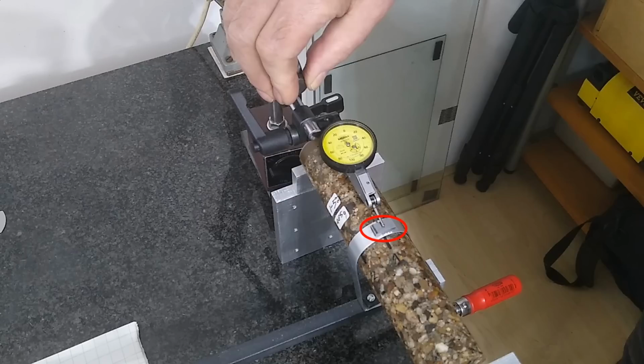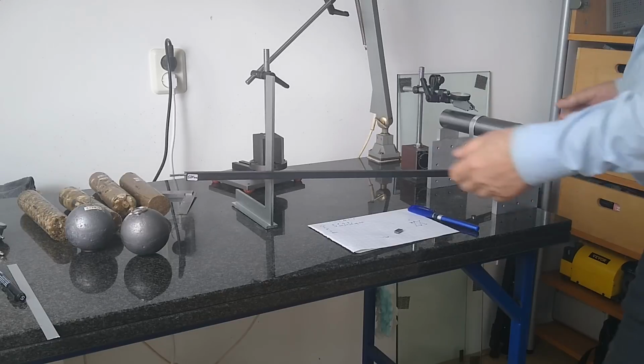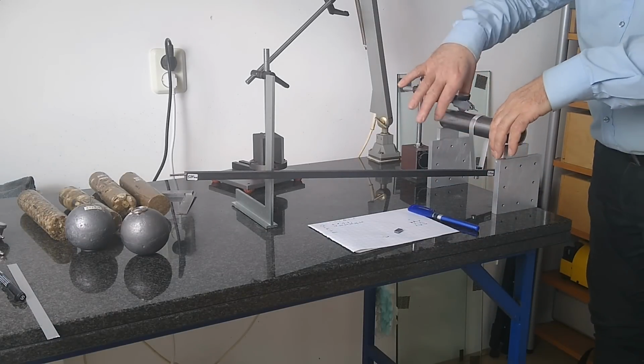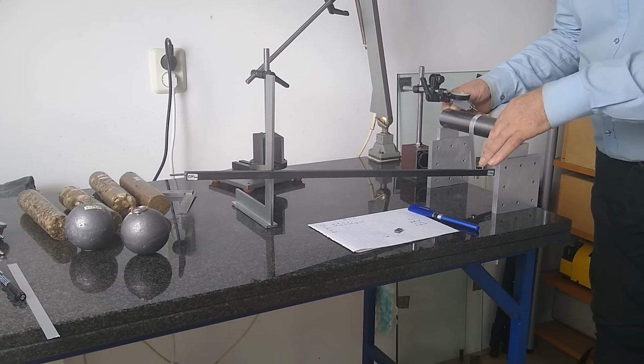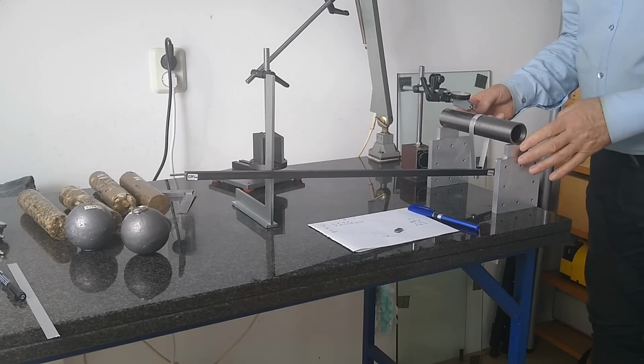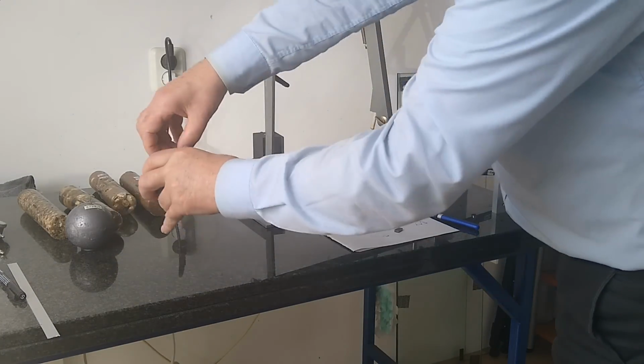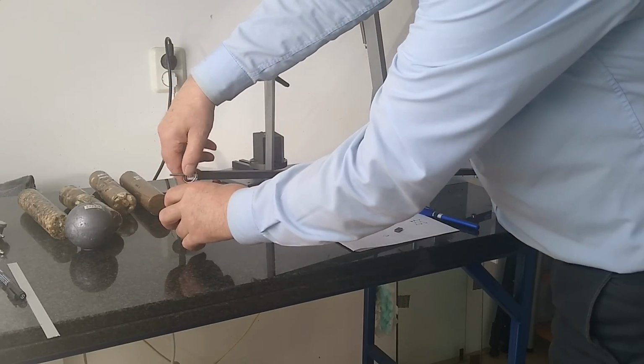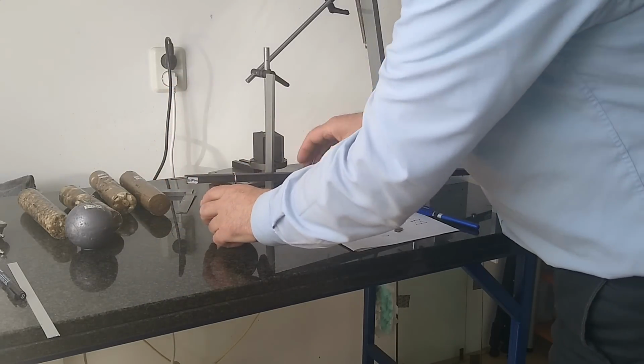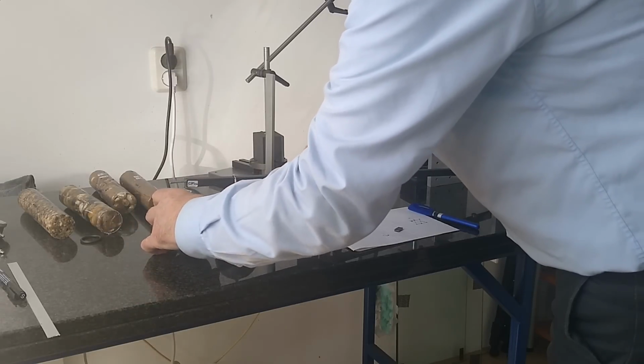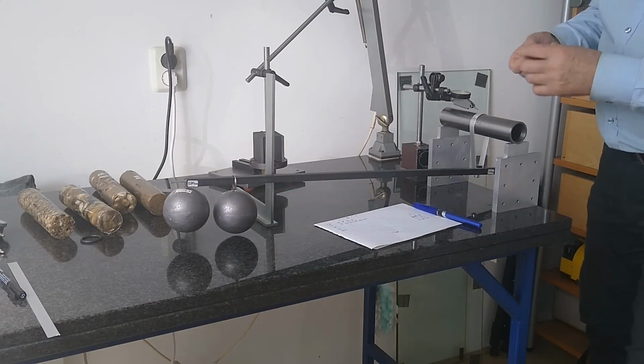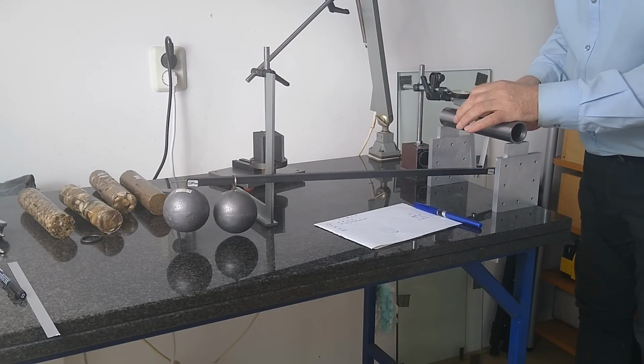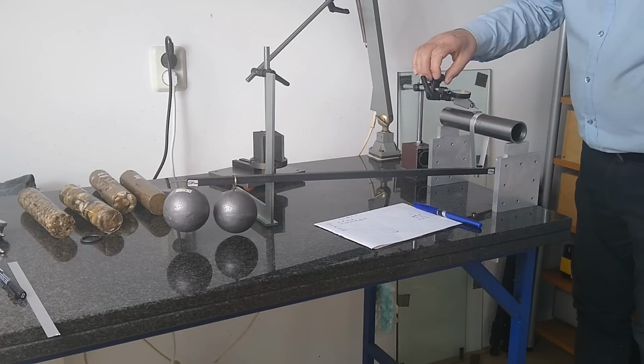I think this is the culprit. I glued a block of steel with a concave bottom to the tension belt on which the indicator probe rests. But that belt can deform somewhat under varying loads, and that deformation is included in the measurement results. Particularly if the surface of a rod is not perfectly round, the resulting deformation can add up to several microns. Essentially, by placing the indicator tip on top, I made the same kind of mistake twice.